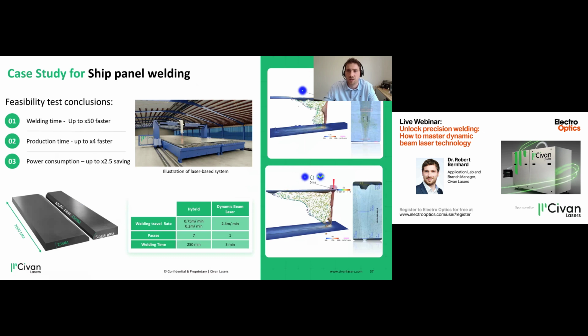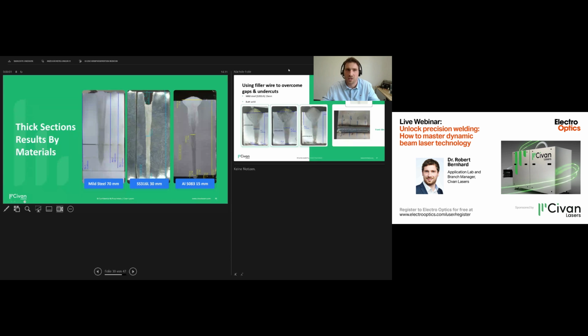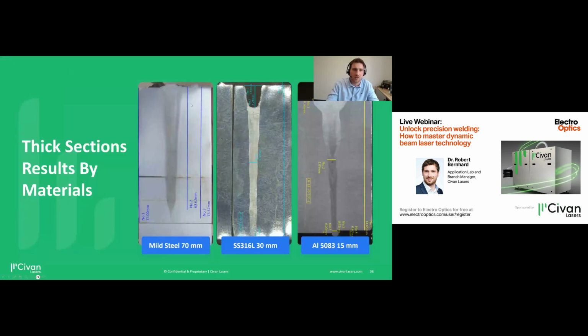And here you can see again the influence of beam shaping, as well as changing between different beam shapes. What this leads to is welding really thick sections. So we're talking about mild steel, 70 millimeters, and welding this with a conventional laser without vacuum, of course, is a challenge. But by also doing the focus steering, we can go very, very deep into the material.